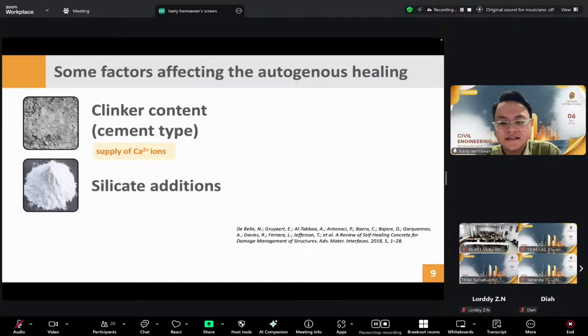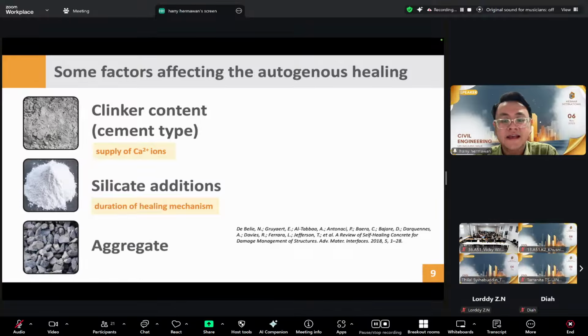Next, the silicate addition also determines the autogenous healing. The silicate addition determines the duration of the healing mechanism due to the characteristic pozzolanic reaction and how fast they will consume the calcium hydroxide from the hydration product of the cement. The third factor is the aggregate, which may also have an effect on the cracking pattern, which indirectly influences the healing process.